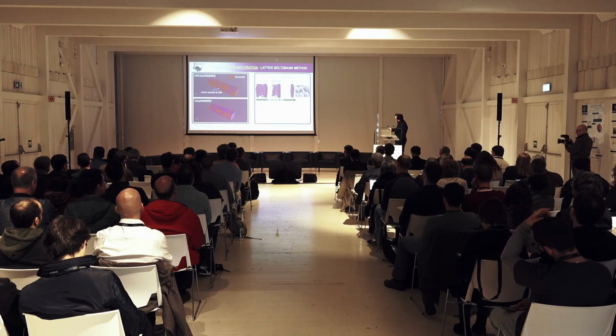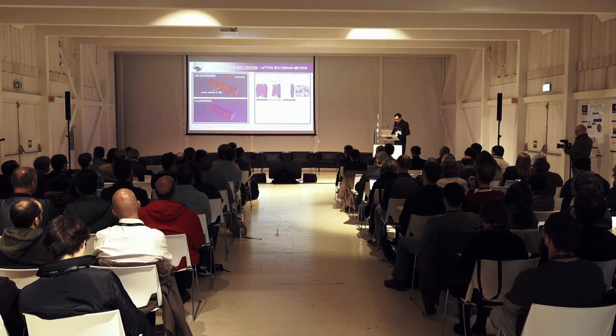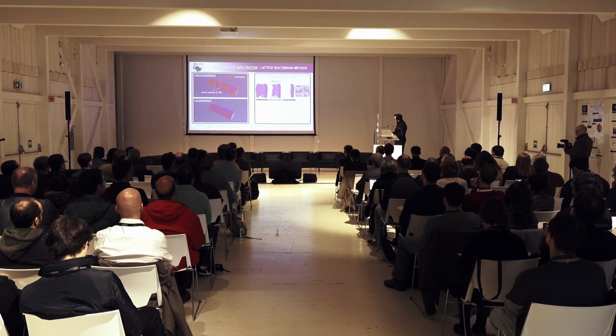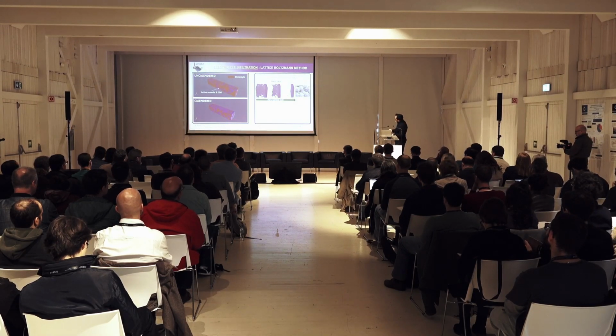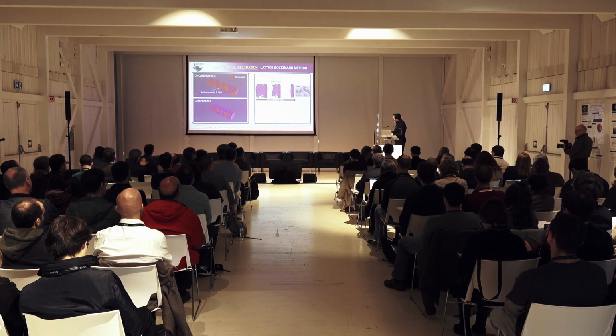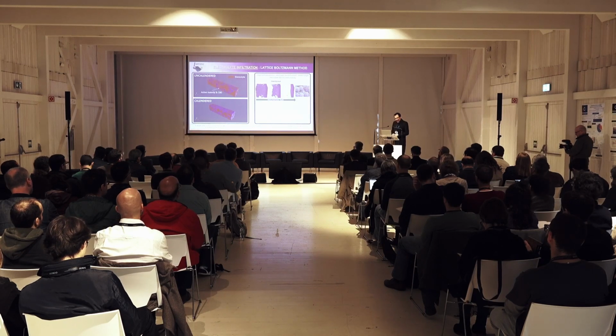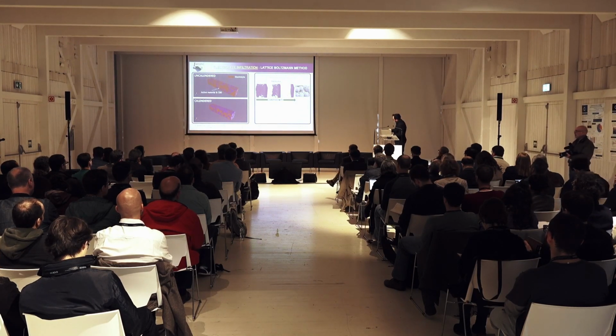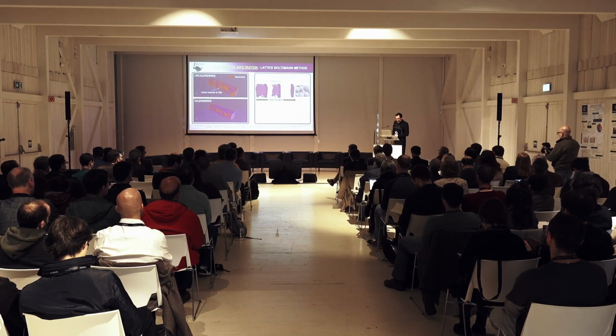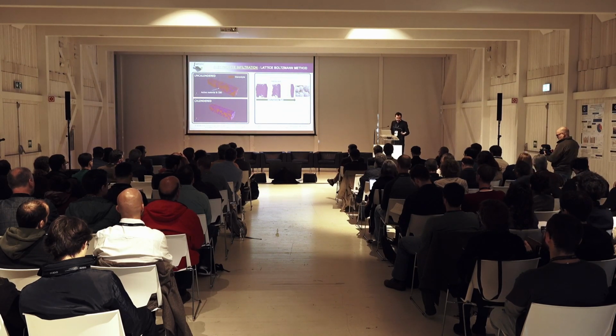Well, the model here, which is based on the lattice-Boltzmann method, is capable of giving insights regarding that. It's also capable of predicting where the air is going to remain trapped inside the pores. Having air remaining in the pores is basically bad for a lithium-ion battery cell because your active material needs to be fully exposed to liquid electrolytes. Okay, and this is something that you want to avoid. You want to avoid having air in contact with active material because then you will lose energy density and power density for your lithium-ion battery cell.